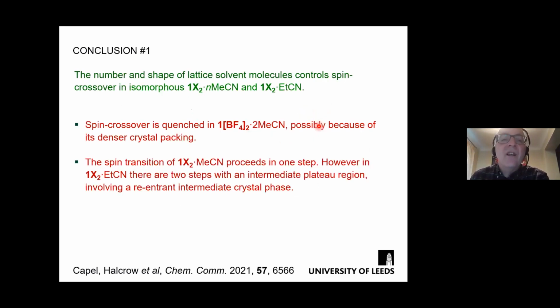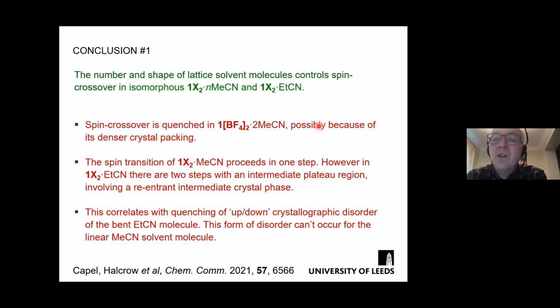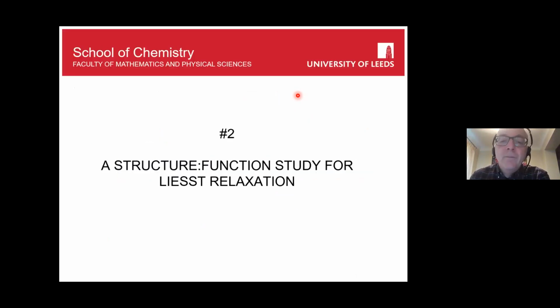And this is a nice illustration of how the shape of the solvent molecule controls the form of the spin crossover we see. It's not the shape of the complex, because the shape of the complex is the same for both of these solvents. It's the shape of the solvent which controls the behavior we see. So that's the first example. The second example is more complicated, and I'm going to present it as a structure function study for light-induced spin crossover, not for the thermal spin transition.